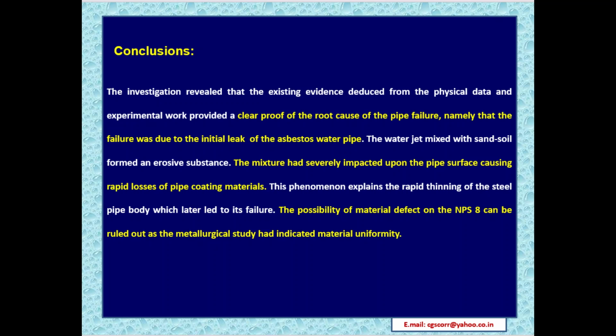Conclusions. The investigation revealed that the existing evidence deduced from the physical data and experimental work provided a clear proof of the root cause of the pipe failure, namely that the failure was due to the initial leak of the asbestos water pipe. The water jet mixed with the sand soil formed an erosive substance. The mixture had severely impacted upon the pipe surface, causing the rapid losses of the pipe coating materials. This phenomenon explains the rapid thinning of the steel pipe body, which later led to its failure. The possibility of material defect on NPS 8 can be ruled out, as the metallurgical study had indicated material uniformity.